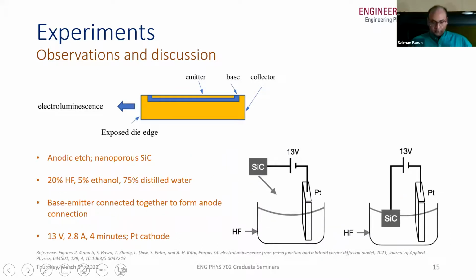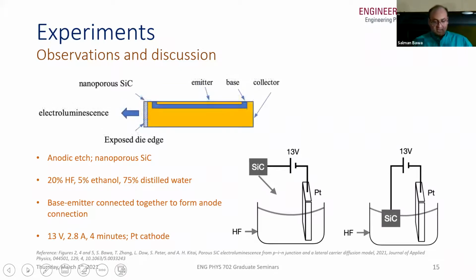And in order to do that, we started off by saying, could we do an etch of the edge of the transistor that we are using? So this is a very well-known anodic etch process to cause nanoporous silicon carbide using 20% HF, 5% ethanol, and 75% distilled water. The base emitter were connected to form the anode connection. Platinum was used as the cathode, and the etch was done at 13 volts, 2.8 amperes for 4 minutes. And diagrammatically, what we get is this etch at the edge of the device that is marked in the figure as nanoporous silicon carbide.